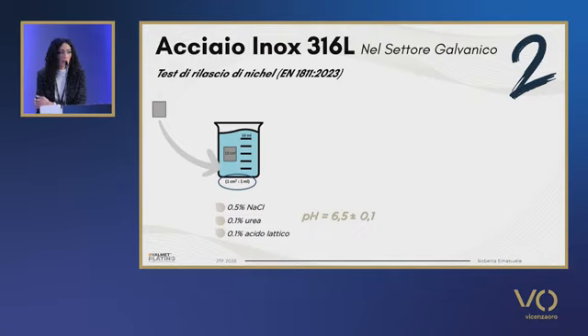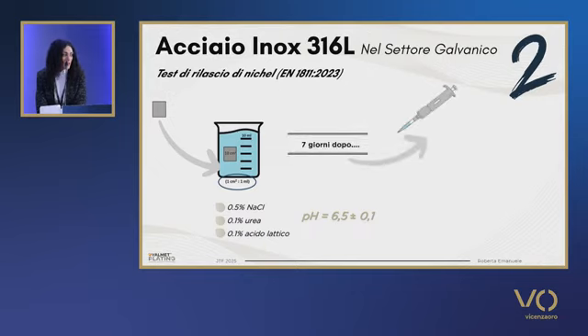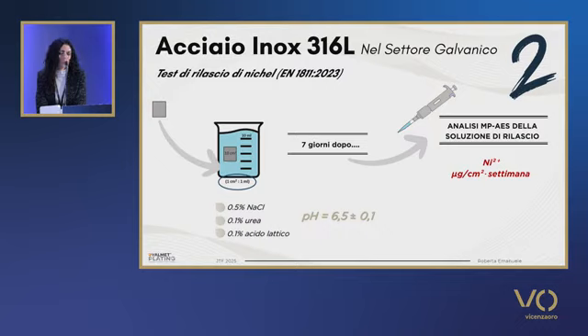The pH should be equal to 6.5 ± 0.1, and the added solution should be proportional to the sample area: 1 square centimeter, 1 milliliter of the solution. So the samples are left within the solution for a week. At the end of the week, this solution is analyzed with MP-AES to understand the quantity of nickel per square centimeter released over the week. We looked at the literature.